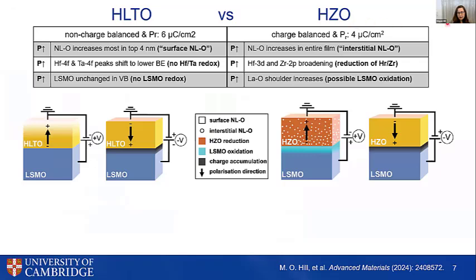So to summarize briefly, we've observed many different things within our samples, and I've had to leave some of them out for time's sake. But in the HLTO, we see for the P-up condition that non-lattice oxygen mostly increases in the top 4 nanometers of our film. Whereas for HZO, we can see anomalous oxygen throughout the entire film. And again, for the P-up condition, for HLTO, we don't observe any effect of hafnium or tantalum reduction or oxidation, but we do see a reduction of hafnia and zirconia in the P-up condition of HZO.